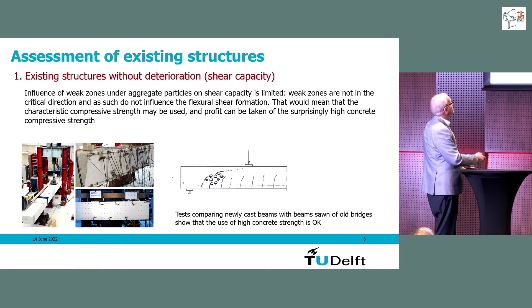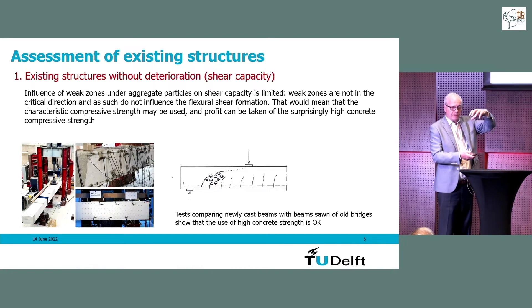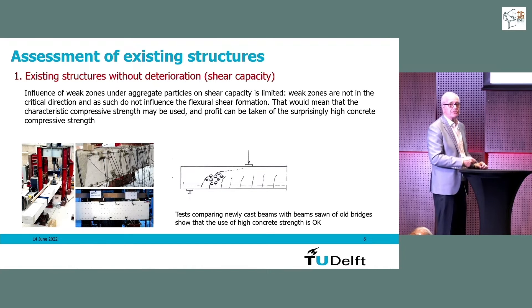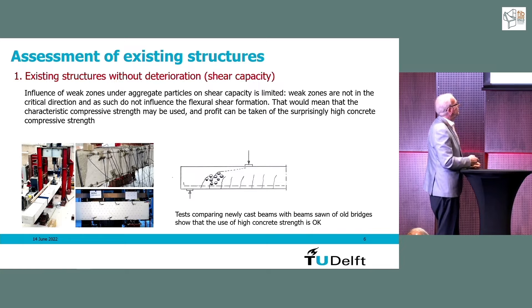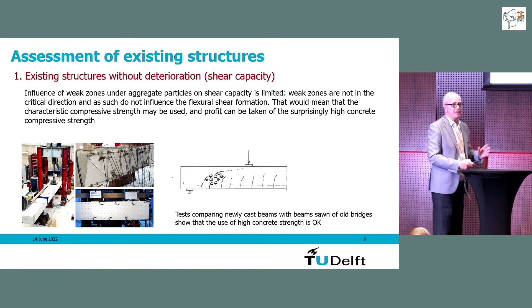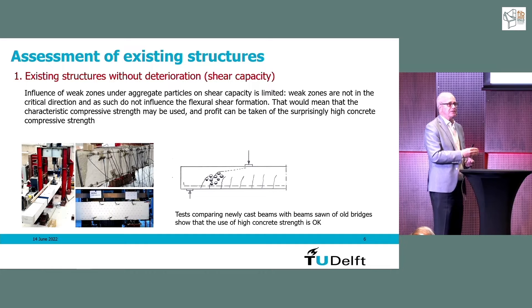We opened the cylinders and found small bleeding voids below the coarse particles everywhere. When you drill vertically and pull, all these weak bleeding areas determine your tensile result. But for splitting and compression it is different. For shear capacity, cracks develop at an inclination that does not interfere much with these bleeding areas. We ran lab tests confirming that the low centric tensile strength values do not interfere with shear capacity — but this is a conclusion you can only reach through testing.